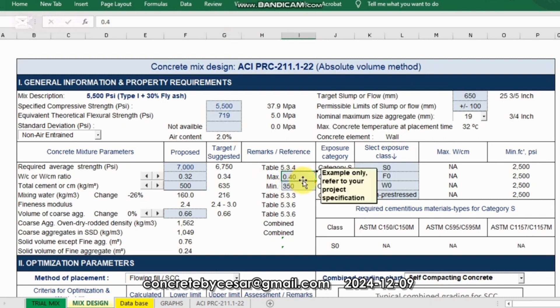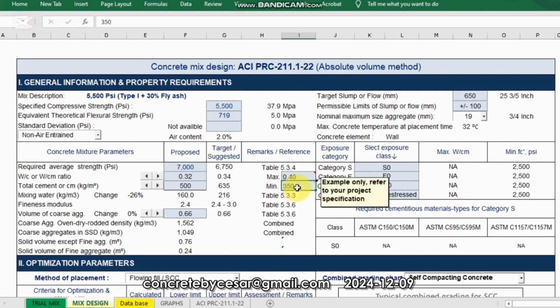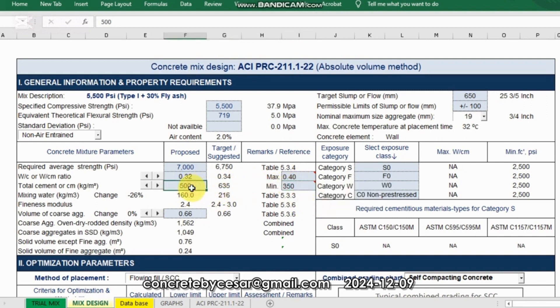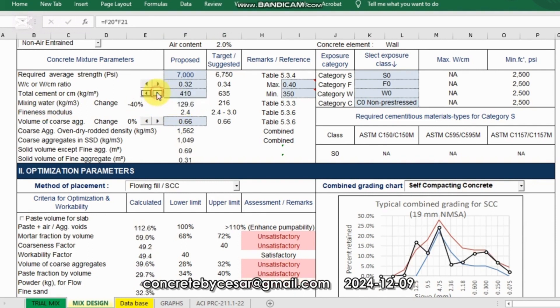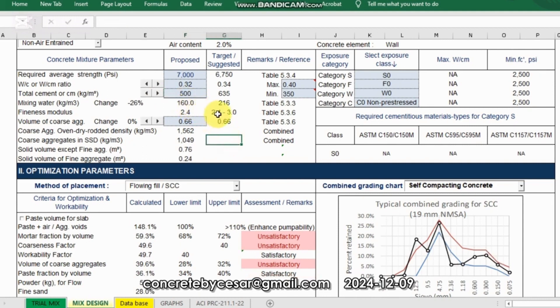Keep in mind that we also have project specifications to consider. Let's say 0.4 is the project-specified maximum water-cement ratio, and the required minimum cement content is 350 kg. These limits will depend on your project specification. For cement, you can always start with the minimum — let's start with 350 kg. You can slowly increase the cementitious content using the increment button while monitoring the SCC parameters below and the water content. I recommend a minimum of 150 kg of water for SCC. In this example, I will jump to 500 kg total cementitious materials, simultaneously observing the changes in parameters and assessment.